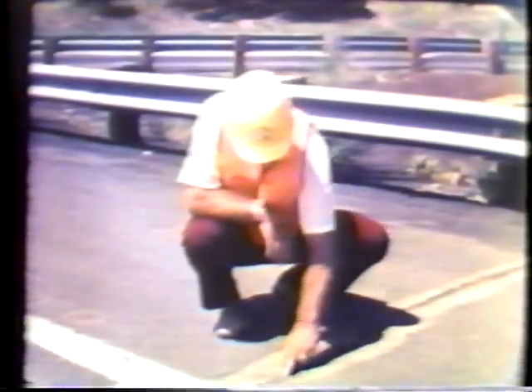Mr. H.G. Lanston, Senior Field Research Engineer with the Arizona Department of Transportation and driving force behind the initial development of Overflex MS: It appeared to me that the greatest cost connected with crack sealing was resealing. In areas of Arizona, using the old process, we were sealing cracks every 4 to 6 months. However, with the asphalt rubber, we have cracks that have been sealed for over 2 years and are still performing beautifully. Other agencies in the state report that the sealant retains its flexibility and ability to seal for 5 years and longer.